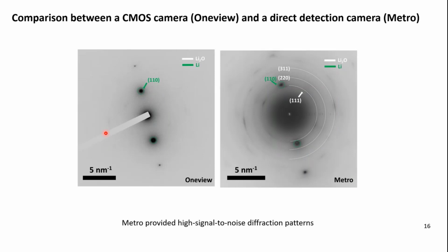I can also point out the capability of Metro by comparing the diffraction patterns between Metro and OneView at the same dose rate. These are the diffraction patterns taken at the same dose rate to emphasize the signal to noise ratio of Metro. I intentionally lowered the dose rate to one that is suitable for Metro and switched between Metro and OneView to see the diffraction patterns. And you can see how clearly Metro provides diffraction patterns of lithium oxide, whereas you cannot see such a clear signal to noise ratio with OneView.